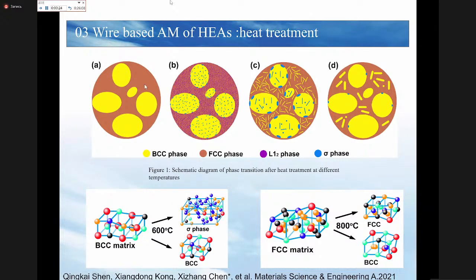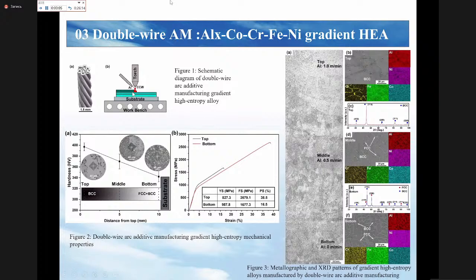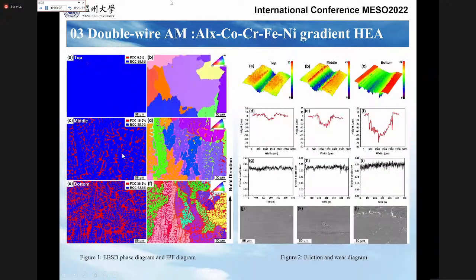We can also use the double wire, where one is the cable wire and one is a single element wire, because aluminum has a bigger effect on the microstructure. So we can change the aluminum composition. From the picture, we can see from top, middle and bottom, the aluminum composition is different and the microstructure is totally different. You can see the picture is more clear. We have no time. Okay. For the picture, we can see the change from almost all BCC to almost all FCC with aluminum change.